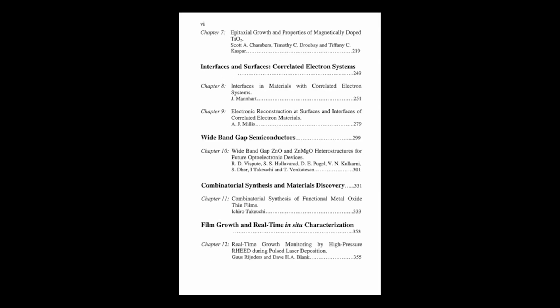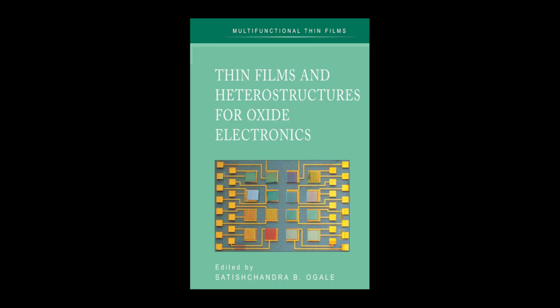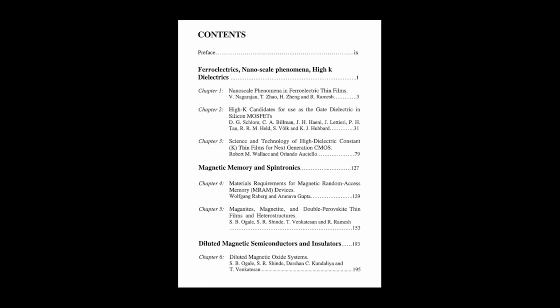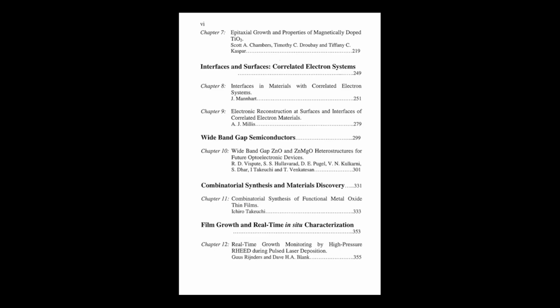And the other way around, a metal becoming insulating at its surface? Yep. Consider a material that's metallic in bulk, like LaNiO3. At the surface, the atoms have fewer neighbors, which tends to narrow the electronic bandwidth W. If W shrinks enough relative to U, the U/W ratio increases, and the surface layers can actually become insulating while the bulk remains metallic. So the interface isn't passive at all, it's actively dictating the electronic phase.